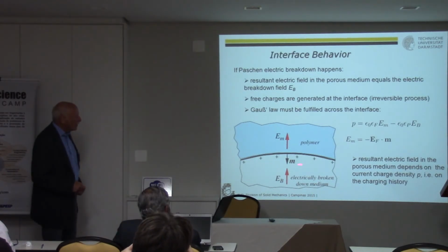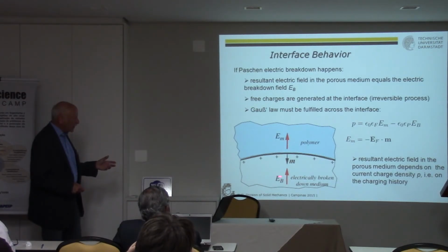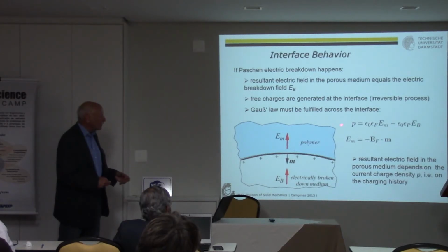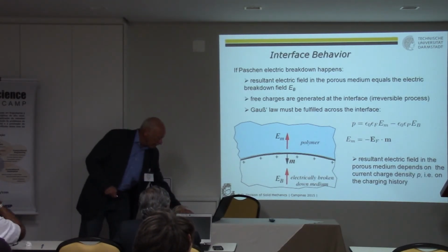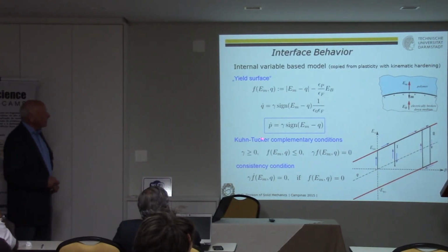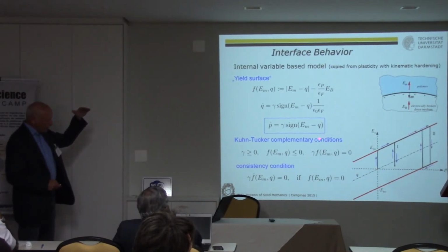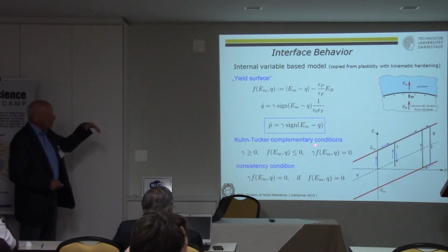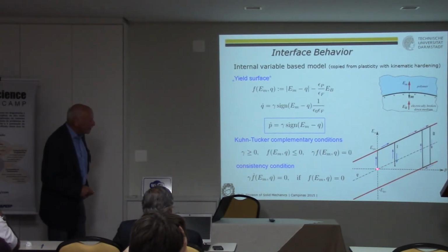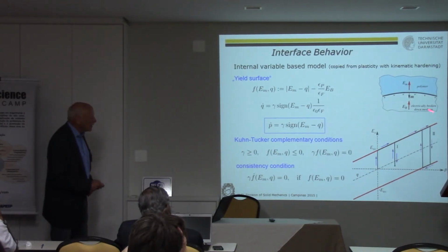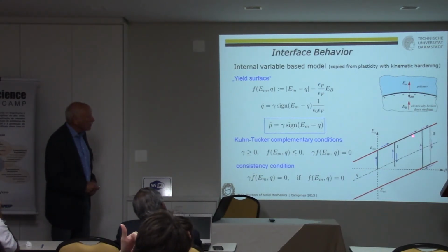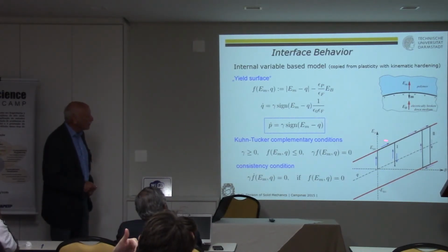And if you have breakdown inside the voids, then the Gauss law is written in this way here, and only in short, what you then can do, look, you load the material, and have your first breakdown. This is given by this line here. You load it. There is not yet any charge at the interface. And here now you have breakdown, and if you increase then the external load, your P, this is the charge distribution at the interface, increases, and it decreases linearly. This is clear also from experiments, yeah.